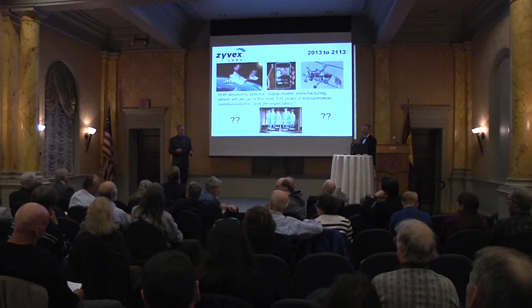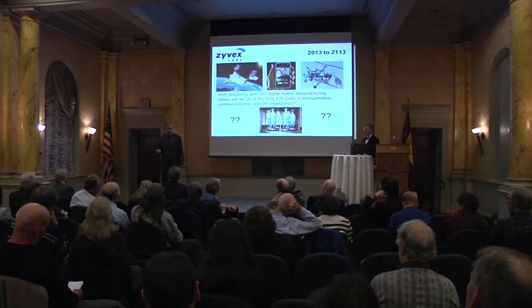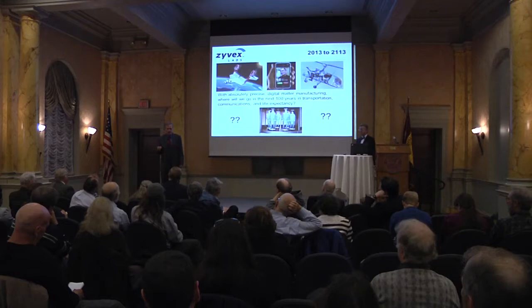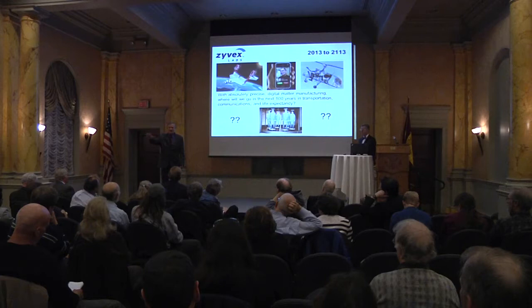Yeah, that's a whole long story. Is the disilane sticking on the tip? I don't have strong evidence that that's happening. I do have annoying changes in the tip that we don't entirely understand. I frankly think that one of the principal culprits is mobile atoms on the surface, especially on the hydrogen passivated surface, that I can't see because they're moving, that sometimes end up between the tip and the sample and cause a momentary short and rearrange the atoms just enough to change the way the imaging and lithography is working.